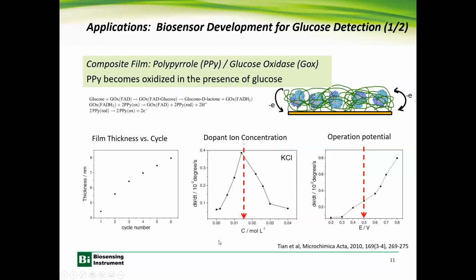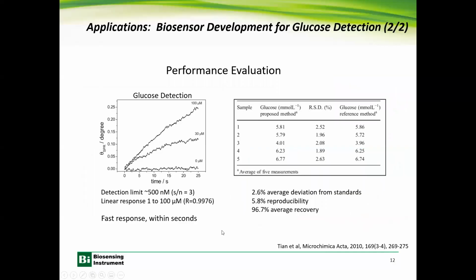potential for the detection. So here are some real testing results for the sensor developed using the method. First of all, on the left side, it shows the glucose detection of 3 different concentrations and the linear dependence between the concentration and the SPR signal. And on the right is a comparison of this newly developed sensor and SPR sensor with some other experimental techniques reported in the literature.